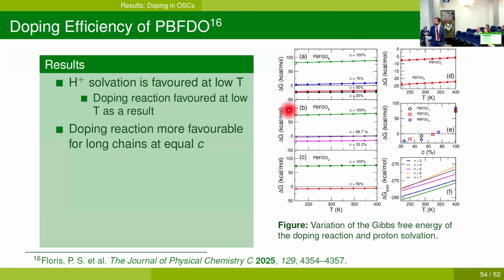So in panel D, we see the delta G of reaction for a PBFDO chain of 2 monomers, of 4 monomers, and of 8 monomers below. So the first thing to say is that these are both at doping concentration of 50%. And of course, the longer chain of 8 monomers has a much more negative delta G. This is to be expected since